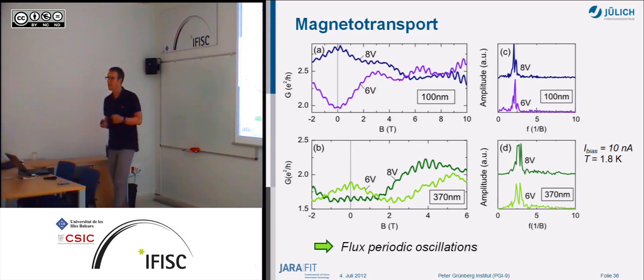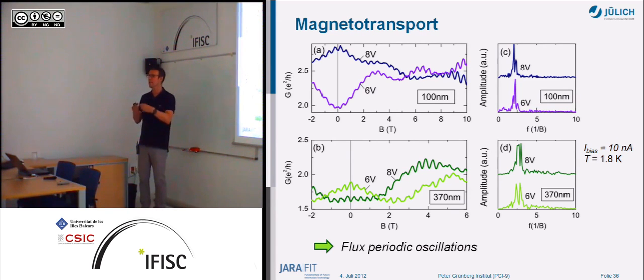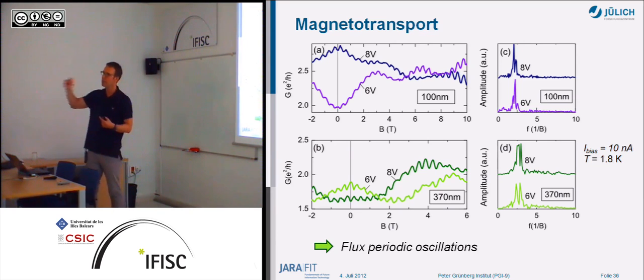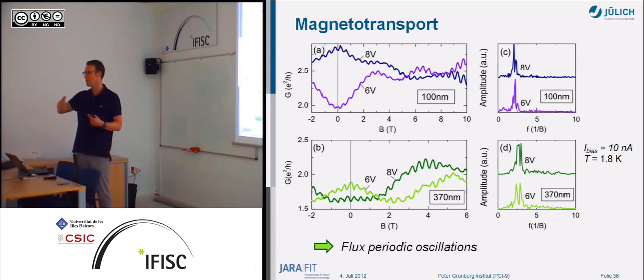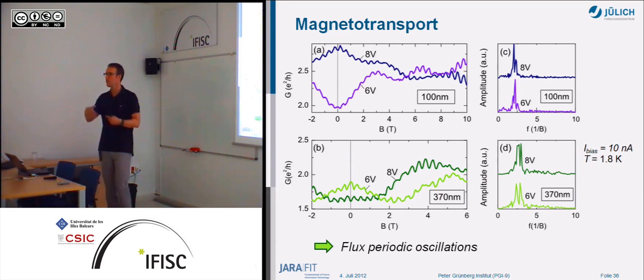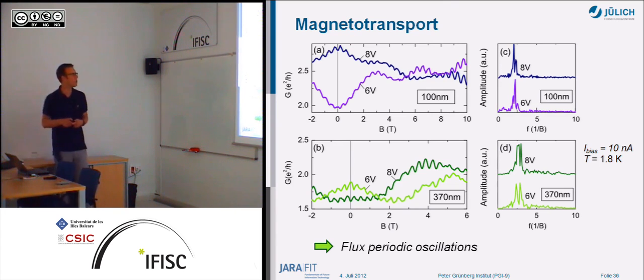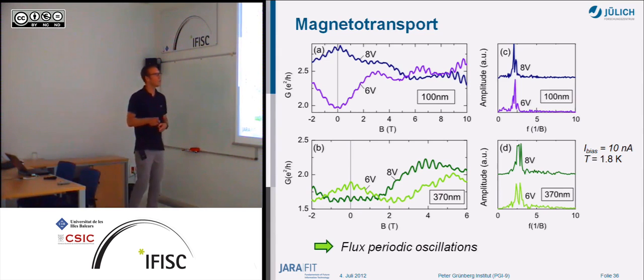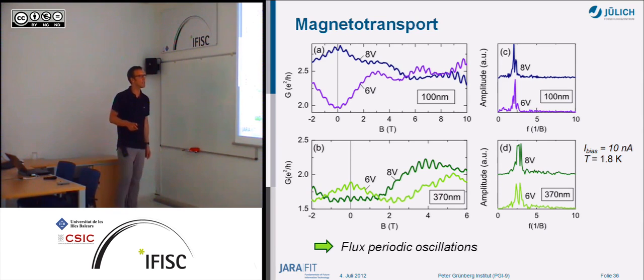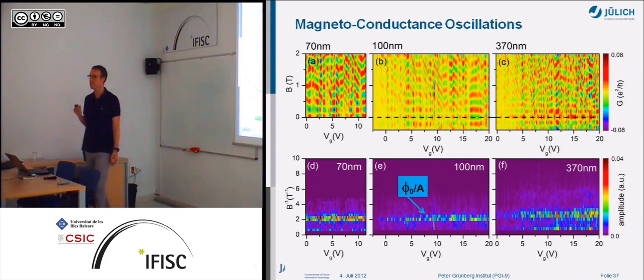And if you calculate and compare that to the magnetic flux, then you see that each time you add another flux quantum to the cross section of the nanowire, you have one period in the conductance oscillation. So that's what we observe. This was for a short piece of nanowire, so the contact separation was 100 nanometers. This was for a longer piece. We also see that the diameter is slightly different because of some growth reasons, but it's still one single flux quantum period. You see the conductance here of the nanowire.